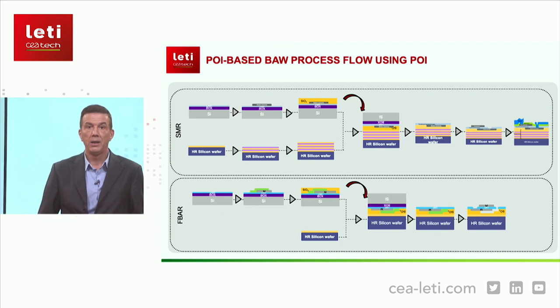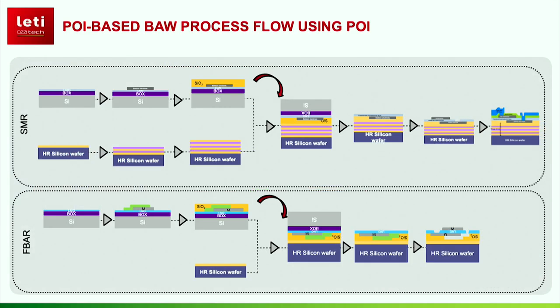So, here is how it works. The starting point for both devices consists of two wafers: the POI wafer and a high resistivity silicon wafer with a thin oxide. For both devices, the first process step is to deposit the bottom electrode on the POI wafer. For the F-bar, a sacrificial layer, in green in the picture, is deposited on top of the electrode. Then for both devices, an oxide is added.